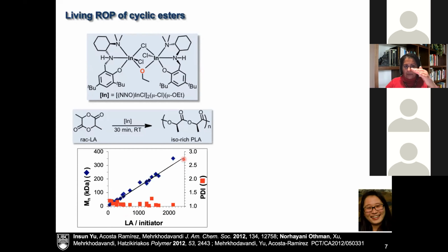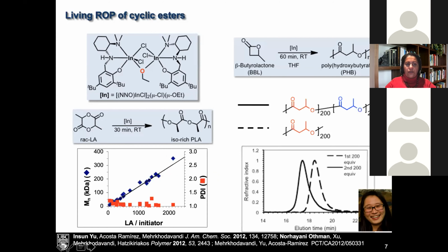So the line here is the predicted molecular weight. It's not a line through the data. This is actually what you would predict. And the blue are actually the polymers that we're getting. So what we're getting are polymers where we have really slowed down or basically stopped any chain end termination reactions. We can do this with a variety of different cyclic esters. I'm just going to show you two of them here. Butyrolactone is a 4-membered one, and it's generally tougher.